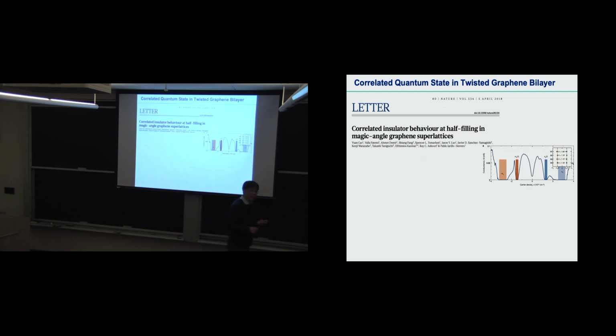So their first paper actually demonstrated that if you just tune this angle between the twisted graphene layers, you create this so-called correlated insulator. Often some people call it the Mott insulator. It was at the middle of the band, but because it's such a narrow band, the gap opens up by interactions and creates a correlated state.